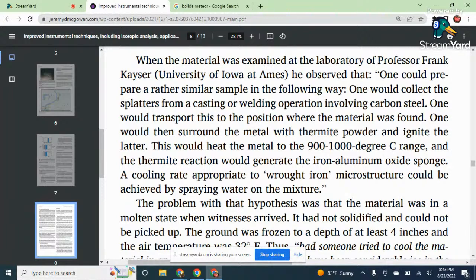So you go to this lake. One would then surround the metal with thermite powder and ignite the powder. This would heat the metal to the 900 to 1000 degrees Celsius range. And the thermite reaction would generate the iron-aluminum oxide sponge. A cooling rate approximate to wrought iron microstructure could be achieved by spraying water on the mixture. Okay, so you have to get this stuff called thermite, and then you have to take your metal and you have to spray it, light the thermite, spray it with water. Sounds a little dangerous, but it was the 70s. What else are you going to do?